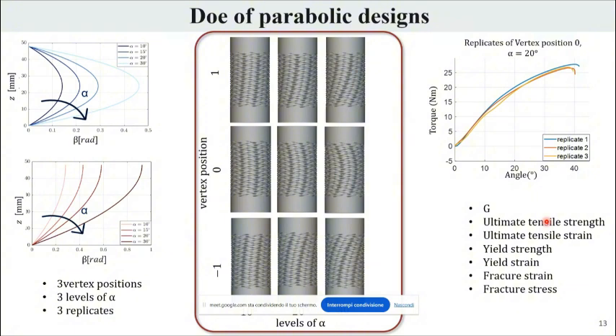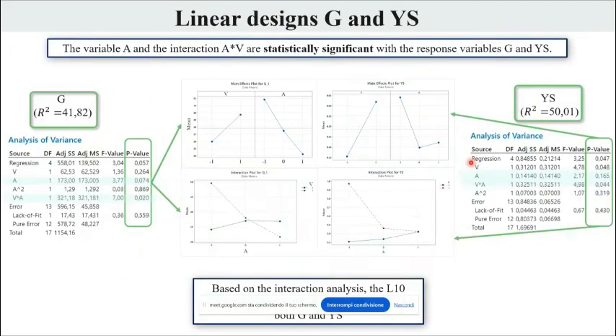This is the design of experiment for the parabolic design. We decided 3 vertex positions, as I told you before. So the one with the center of the parabola in the half of the specimen, and the condition in which the vertex of the parabola is in the upper and in the bottom part of the specimen. And again, alpha varies from 10 to 30 degrees in 3 levels. We performed 3 replicates, and then again, we extracted the most important parameters.